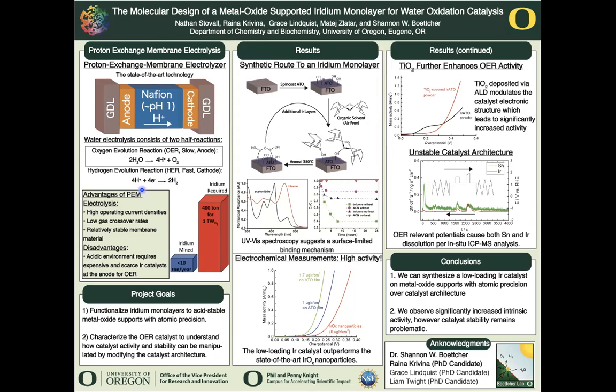But actually, I studied the oxygen evolution reaction, interestingly enough. So why do I want oxygen if we really want hydrogen? Well, actually, you can't get one without the other. You have to do both. And it turns out the oxygen evolution reaction is rate determining. It limits the rate at which you can split water. And to aid in this, we want to develop a catalyst.